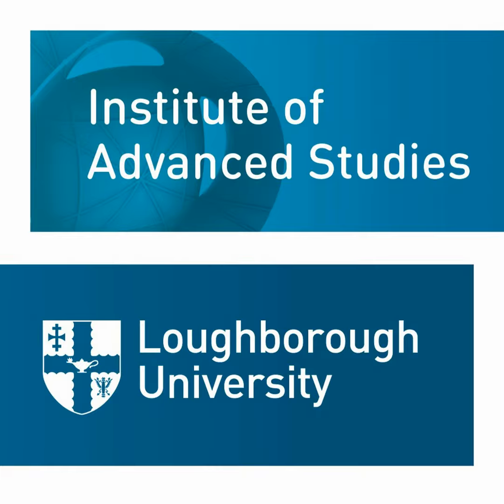And about 20 years ago, when I was at Yamaguchi University for my PhD degree and postdoc, I did a lot of research on hydrocarbon-based PEM, proton exchange membrane, including sulfonated polyether ketone, sulfonated polyphenylene sulfide, sulfonated polysulfone, and sulfonated polyimide, etc. And you can see all the hydrocarbon-based PEMs shown in this slide are called main chain type. That is, the sulfonic acid group is bonded directly to the polymer backbone. We call these main chain type polymer electrolytes.